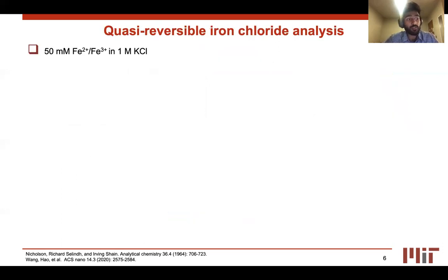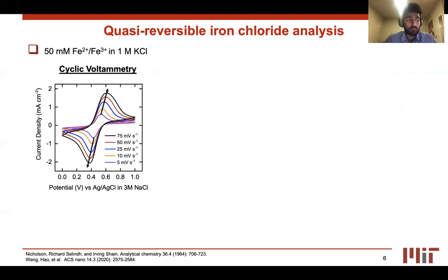The synthesized non-porous and planar carbon electrodes were tested in iron-based electrolytes. In the quasi-reversible regime, 50 millimolar iron chloride in 1 molar KCl was analyzed. First, a CV analysis was carried out to determine the anodic and cathodic peak-to-peak separation. The peak anodic and cathodic currents were also extracted by background subtraction of the non-Faradaic current contribution using a linear baseline.